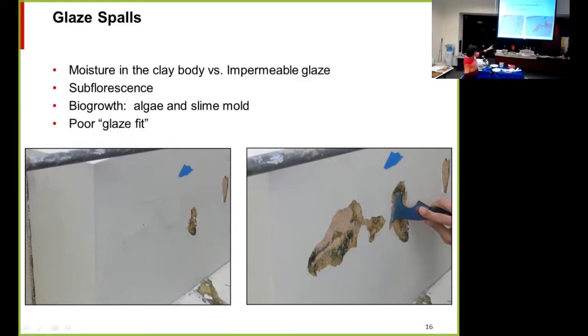And you can start chipping out around a glaze spall that you see, like I'm doing there on the right, and you'll just get more and more of the glaze that's loose and has algae under it and that comes off. So that's one reason. Another reason that we see less commonly is poor glaze fit. So that you don't see it anymore because the manufacturing of terracotta is so much better. But if the coefficient of thermal expansion of the glaze and the clay is different, then it has poor glaze fit. And as it goes through temperature changes, or even just as it comes out of the kiln and it's cooling off, the glaze can spall off.